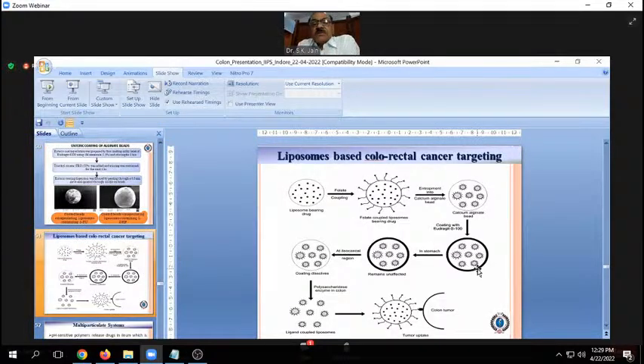This is the liposomes based colorectal cancer targeting. So we prepare liposomes and incorporate an anti-cancer drug, and the surface of the liposomes is decorated with folic acid. And these liposomes are entrapped in calcium alginate beads, right? And these calcium alginate beads are further coated with an enteric coating polymer like Eudragit S, right? When these beads are delivered through the oral route, they will be intact in the stomach because they are enteric coated, right?